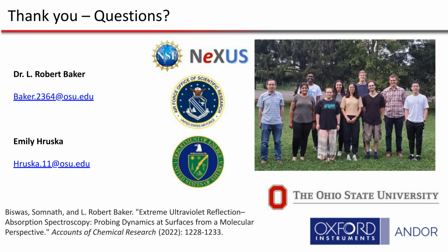In the transmission samples, as your XUV beam goes completely through the sample, you will have an effect of the absorption of the bulk of your sample. And because the bulk can have different properties and behaviors than the surface, your output data will have a lot of information on the bulk. Depending on what you classify as the surface, which in our group would be the first few nanometers, if you go through 100 nanometers of sample, you really can't say much about what you're detecting at the surface. You'll have too much interference from the bulk. And I think this is one of the biggest benefits of XUV reflection experimentation, where you can just isolate what's happening at the surface layer.